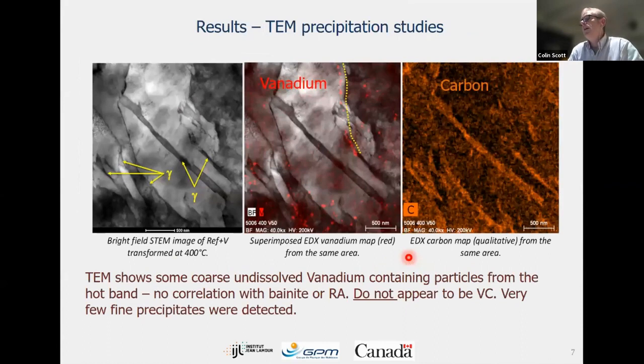We did a lot of precipitation studies as well. So here's an example, bright field image. You can see retained austenite. These are these dark laths here. And then there's bainitic ferrite between them. You don't really see any precipitation or strong precipitation in this image.